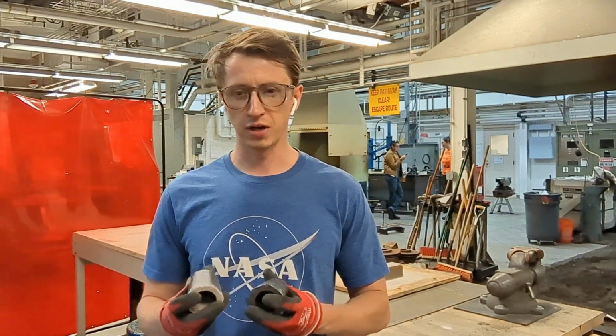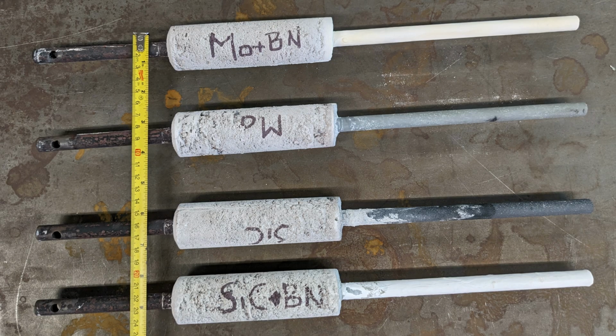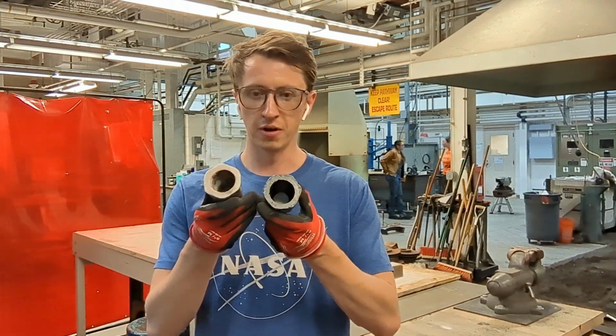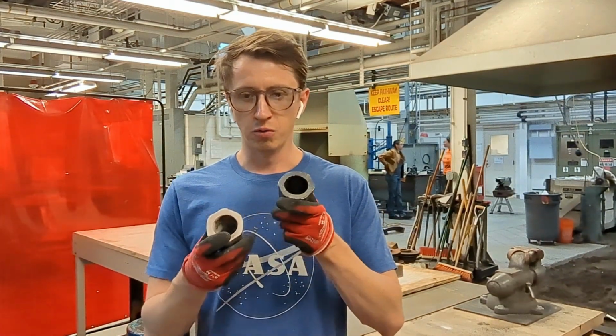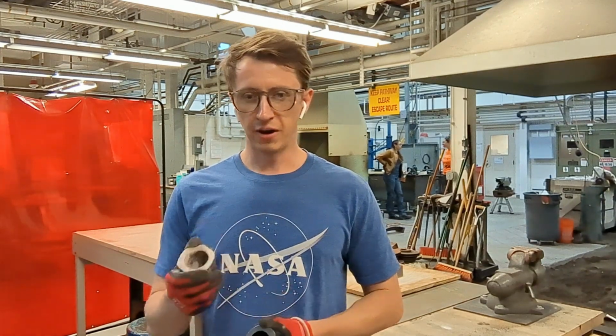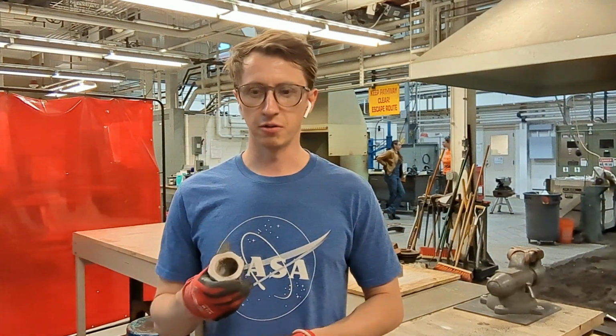This test was the second static dwell and also the static holding of the cooling of the refractory crucibles. For this test, 2 silicon carbide and 2 molybdenum rods and crucibles were tested. 1 rod and crucible of each was coated with boron nitride, and the other was uncoated. 5 layers of aerosol-based boron nitride were applied, ensuring each layer was dried before the next application.